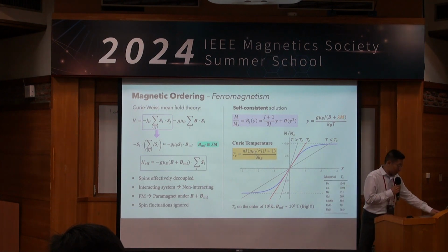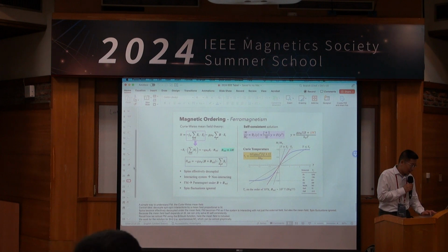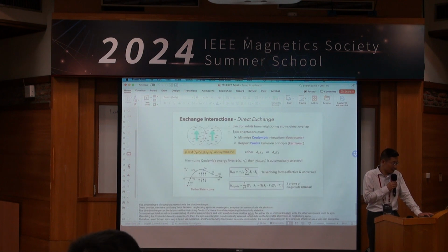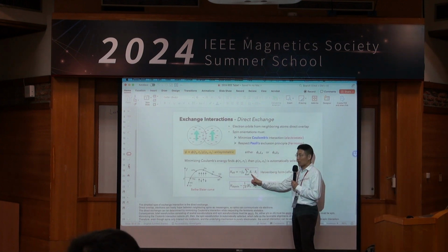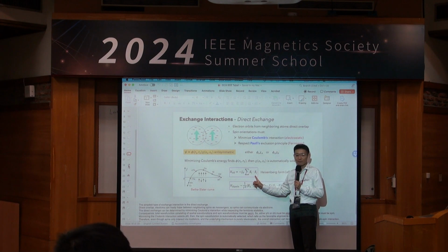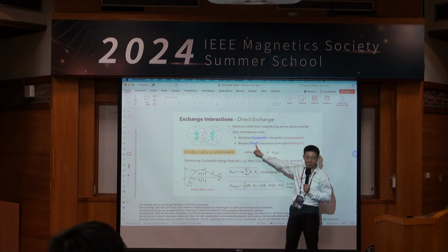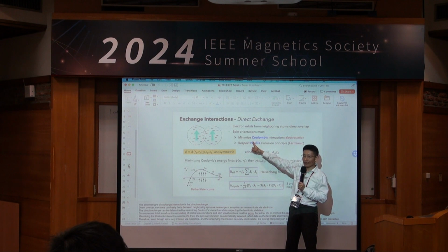It only effectively couples to spin by simultaneously minimizing the Coulomb interaction and satisfying the fermionic statistics. So here, the Heisenberg interaction couples spin. It's a spin-spin interaction. But our starting point has nothing to do with the spin other than the Pauli exclusion principle serving as a constraint. So the interaction has a pure electrostatic origin.